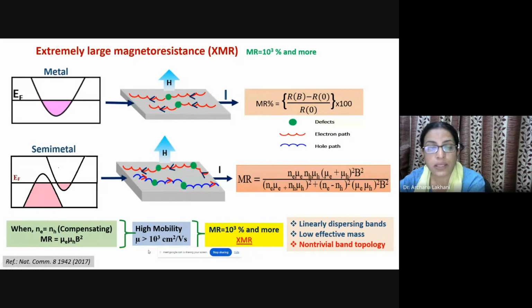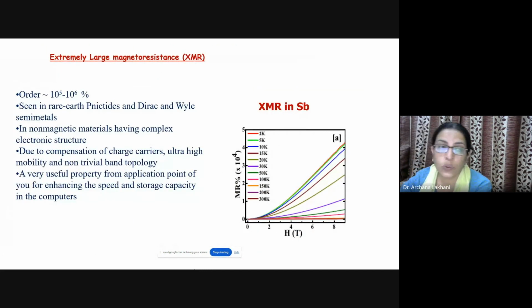And such a large, extremely large magnetoresistance is supposed to be because of the compensation present in the material, and very high mobilities. And it is said nowadays, in terms of quantum materials, as we call them, they have non-trivial band topology, which also causes extremely large magnetoresistance in these materials. So we see almost 10 to the power 5 to 10 to the power 6 percentage change in these materials. It is seen in many rare earth pnictides and Dirac and Weyl semimetals.